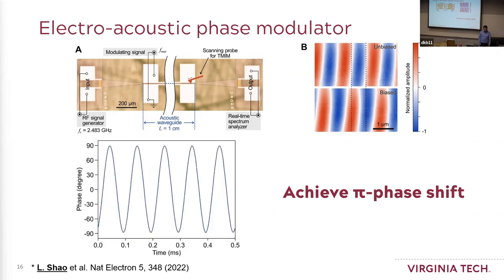This clearly shows it in the spatial domain. And if we apply a large enough sine wave to this electrode, we measure the output phase, and we can achieve a high phase shift. Basically, with a single pump signal, you can achieve a high phase shift, and you can get every phase you want. It's okay because it's plus or minus pi. Yeah, you get everything you want. And this is phase modulation.